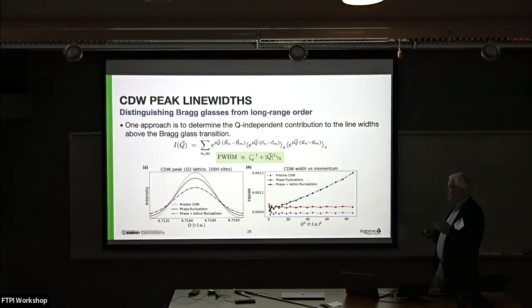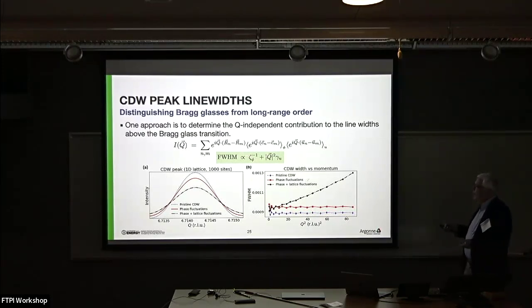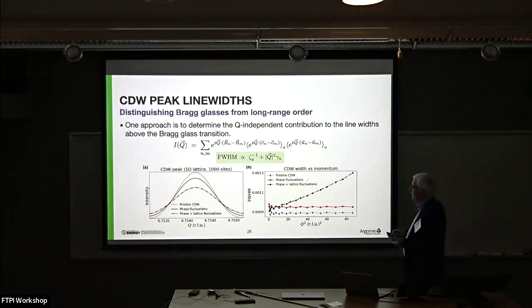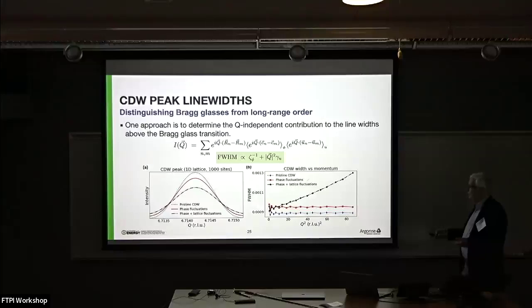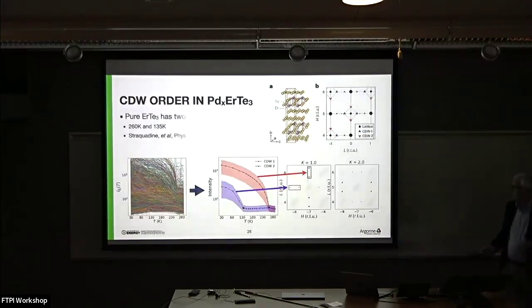This is now coming down to the Bragg glass transition. The idea being that phase fluctuations would have a Q independent line width, whereas fluctuations due to lattice displacement will have a Q dependent one. And so if you can separate out the Q independent part of the line width, then you can determine whether that diverges in a way that's consistent with Bragg glass.